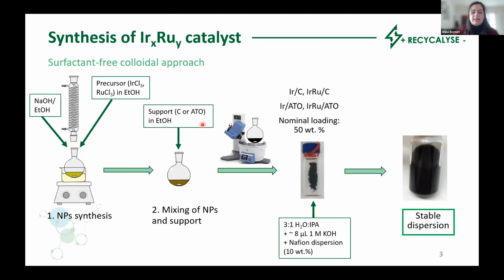Then the solvent is evaporated, and I obtain this catalyst powder of either iridium or iridium-ruthenium on either carbon or ATO, all of them with a nominal metal loading of 50%. This means that the catalyst is composed of 50% nanoparticles and 50% support. Then this powder is dispersed in a solvent mixture, and I obtain a stable dispersion. The stability of this dispersion is an important property, as we will use it later to prepare our electrodes.